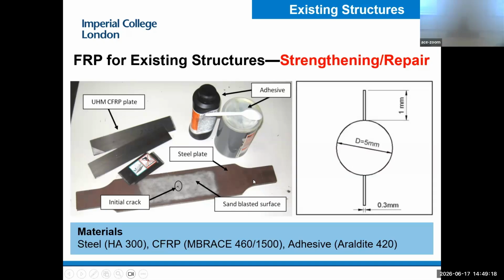This is a very simple steel plate, and in the center we have a prefabricated crack. Before bonding FRP on the surface, we have to carefully treat the surface for better bonding quality, so we used sandblasting. As you can see, the surface is cleaned, and we use epoxy to bond the two materials together.